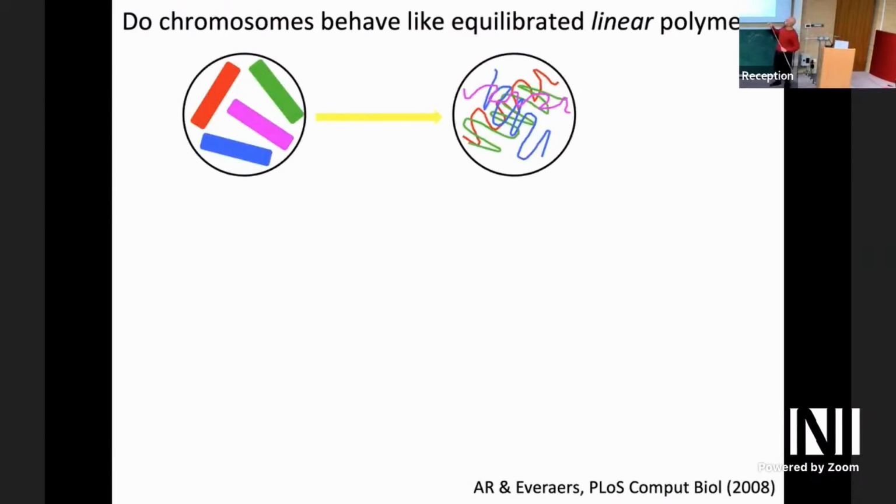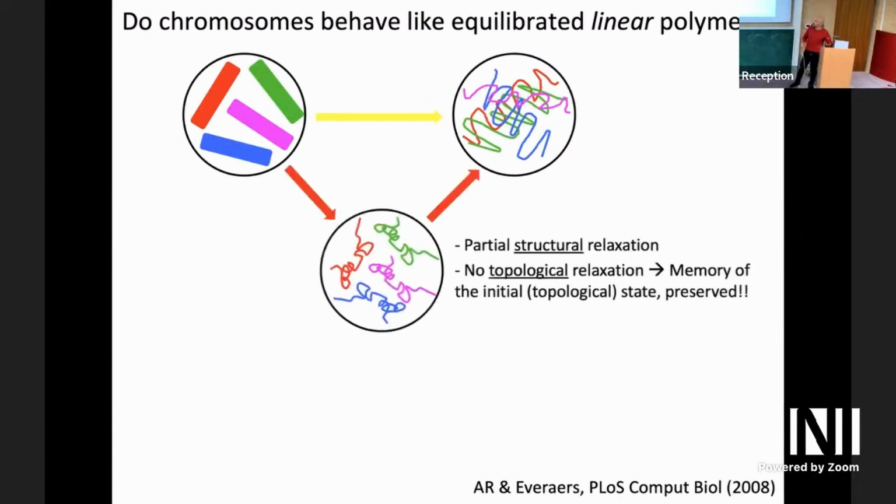So, in fact, precisely as you pointed out, our structures are never in equilibrium, in the following sense. If you start from polymers which are very well separated from each other in some box, and then you allow them to equilibrate, of course, just by thermal motion these things will become disordered. But there are actually two mechanisms toward relaxation, which are very well separated in time. One is some partial local relaxation, but at some point the polymers will just bump into each other and get stuck because of the topological impediment that is in place.